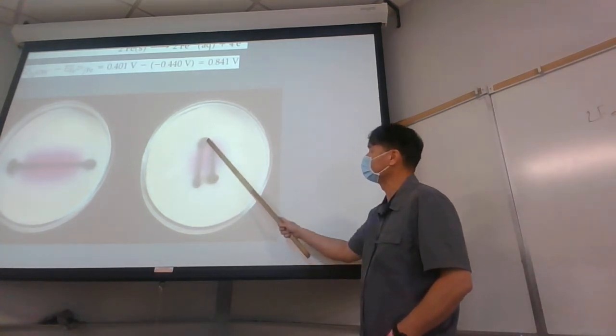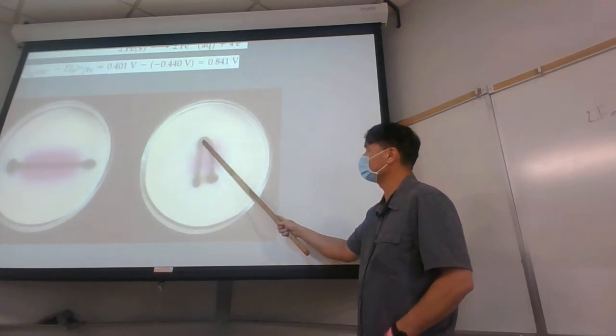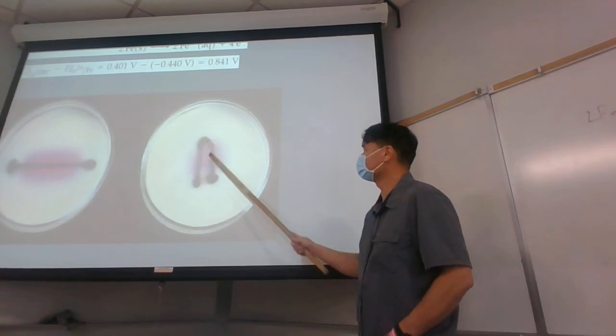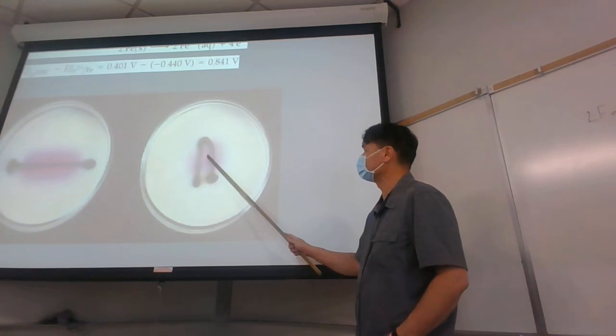Okay, this is another iron nail, but this iron nail's been hammered on the ends and bent. When you bend it, you create defects here, and those defects are going to make the iron more susceptible to oxidation, increase its oxidation potential. And so we have 3 anodes, here, here, and here, and 2 cathodes in this case.